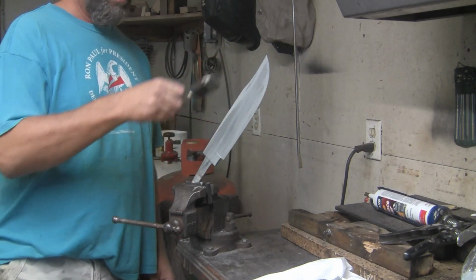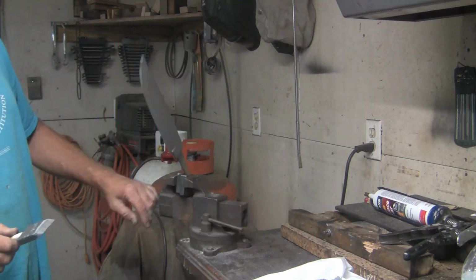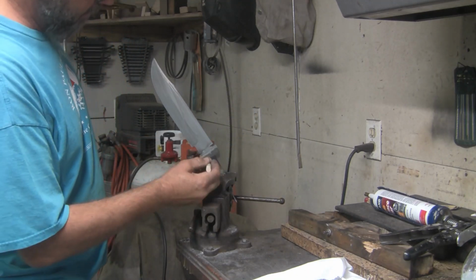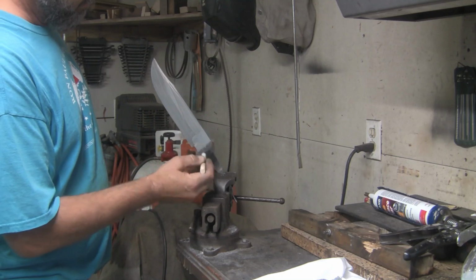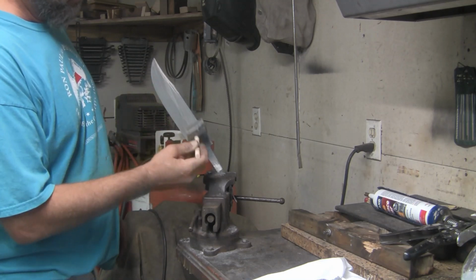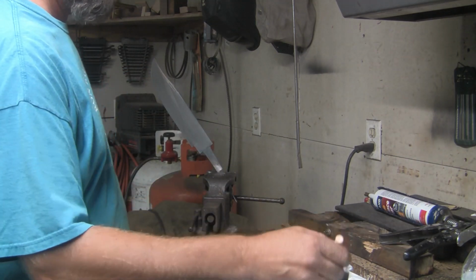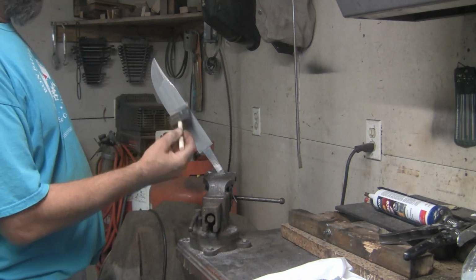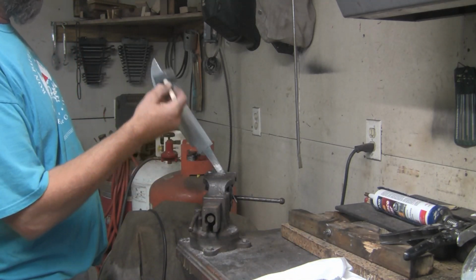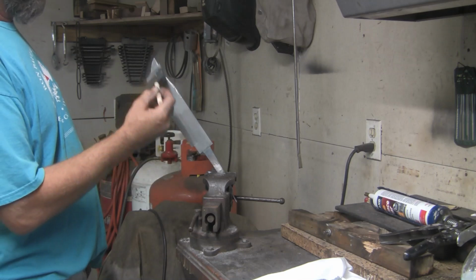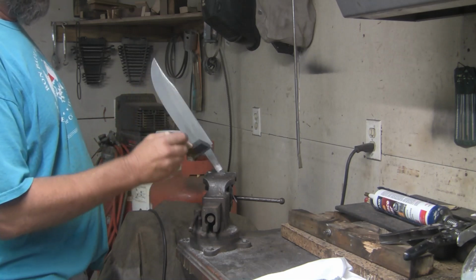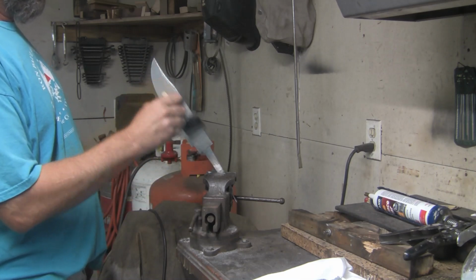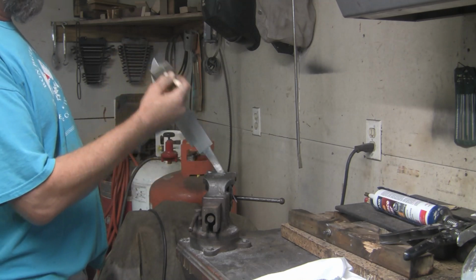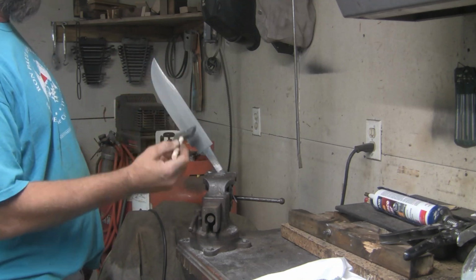So I don't want to get this too thick, but I do want a nice base that the tempering clay, it's actually going to temper the thicker parts of the steel during the quench. I want to give it something good that it can stick to.